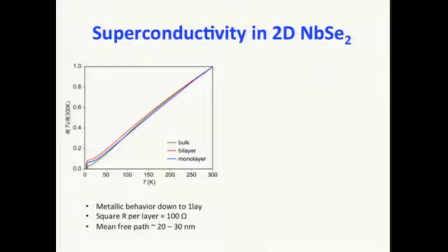Besides optical spectroscopy, now we have the electrodes contacting the material, so we can actually measure the resistance. This shows the resistance as a function of temperature normalized to the resistance at 300 Kelvin for better comparison between the bulk material with the monolayer material as a function of temperature. And you can see that resistance increases almost linearly with temperature, indicating just metallic behavior is still maintained